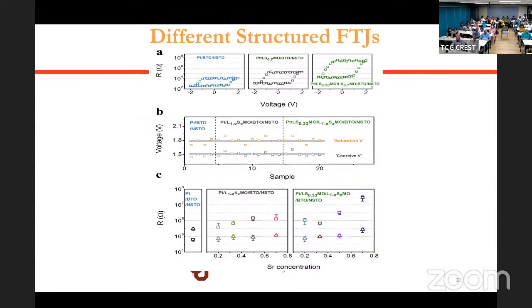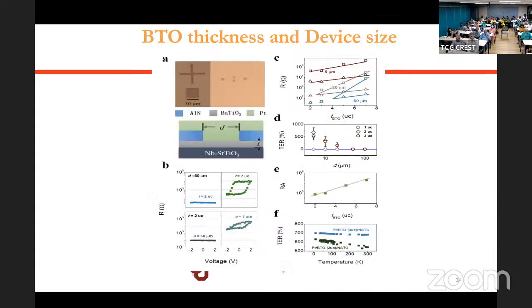The other interesting thing we noticed in these tunnel junctions is that we can actually reduce the number of unit cells of the ferroelectric. So right now in this case, you're down to almost 2 unit cells of ferroelectric, and still you have this characteristic hysteresis here. So even with 2 unit cells, we can see ferroelectric behavior. At one time, the theorists believed that for a ferroelectric to know it's a ferroelectric, it needs to have at least 3 unit cells. But now it clearly shows that no, that's not true at all. We are down to 2 unit cells.